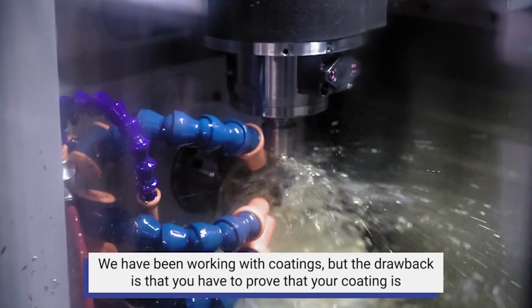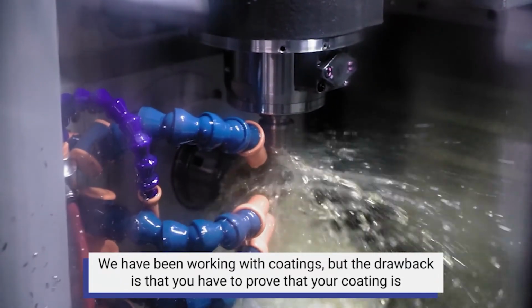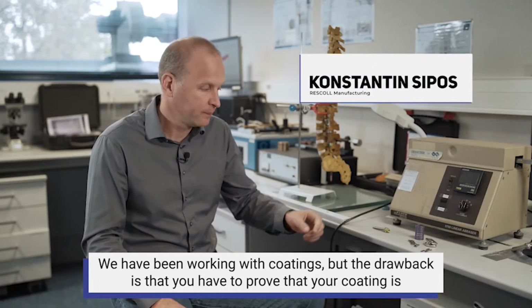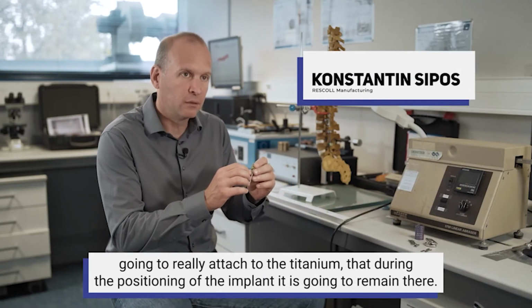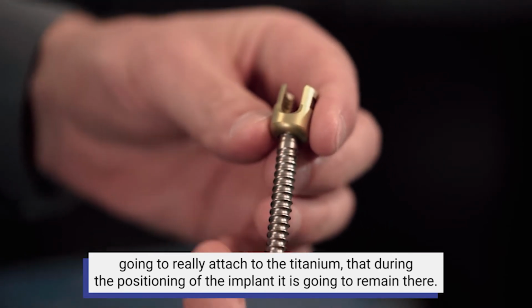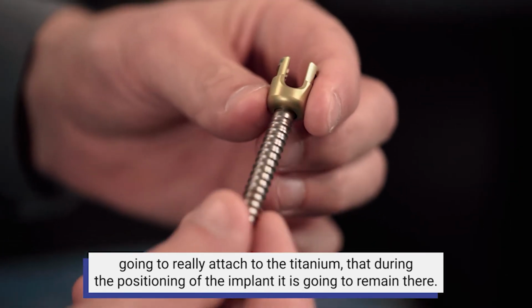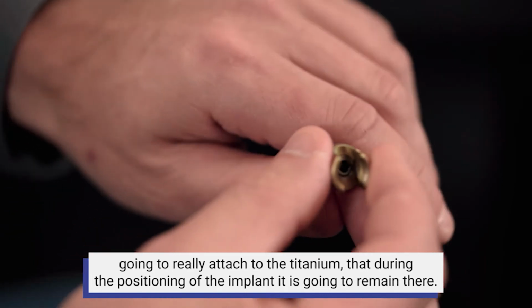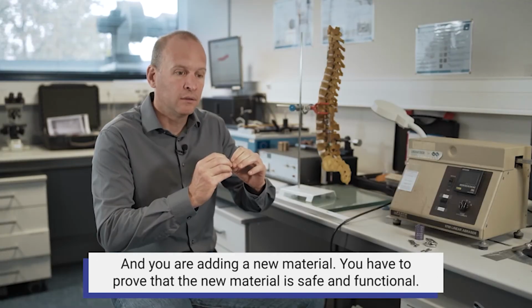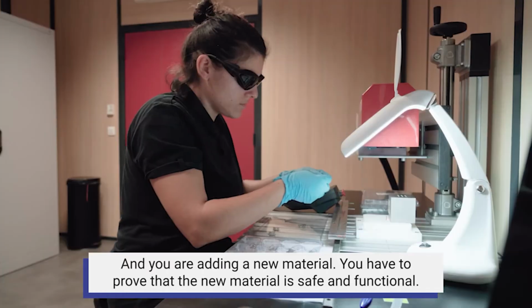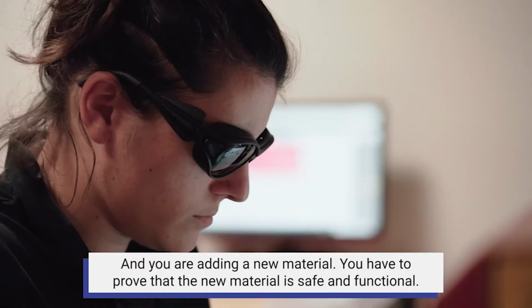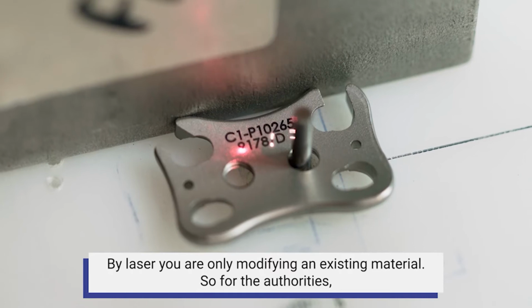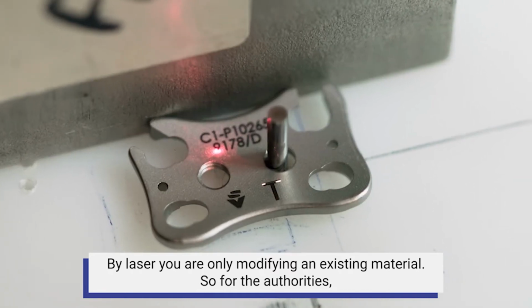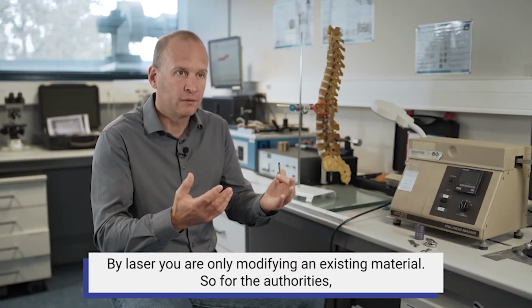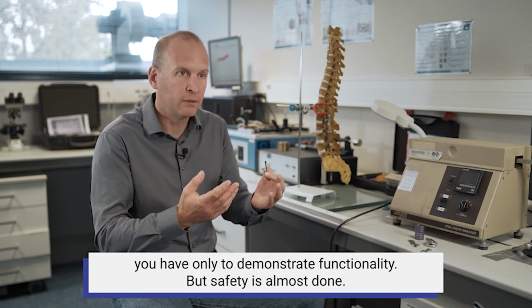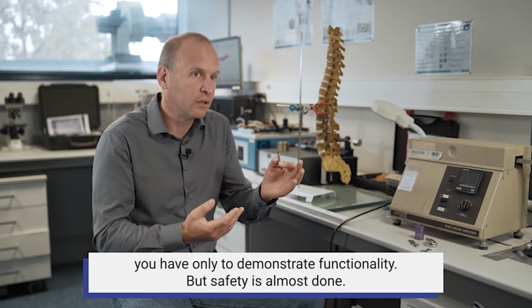We have been working with coatings, but the drawback is you have to prove that your coating is going to really attach to the titanium, that during the positioning of the implant is going to remain there, and you are adding a new material. You have to prove the new material is safe and is functional. By laser, you are only modifying an existing material. So for the authorities, you have only to demonstrate functionality, but safety is almost done.